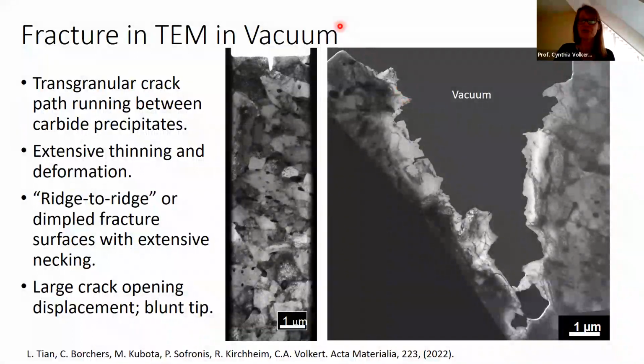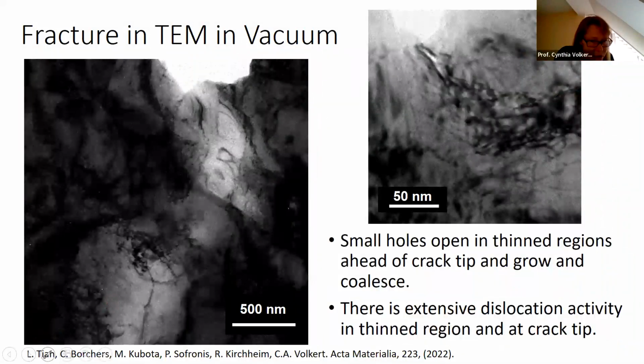We see that we have a transgranular crack path that's running between the carbide precipitates. There's been a lot of thinning near the crack front, a lot of deformation. And important is that we have a ridge to ridge or dimpled fracture surface with extensive necking. You can see the necking here, and where there's a valley on one side, there's a valley on the other, so they are mirror images of each other. And it's a very blunt tip that we produce. And now I'd like to show you a video of this.